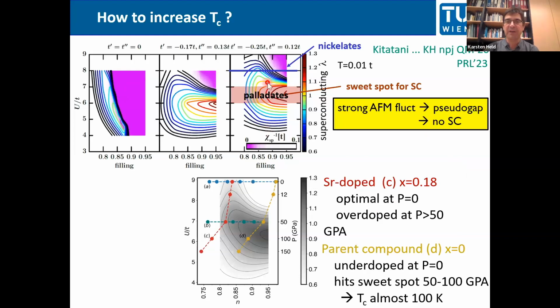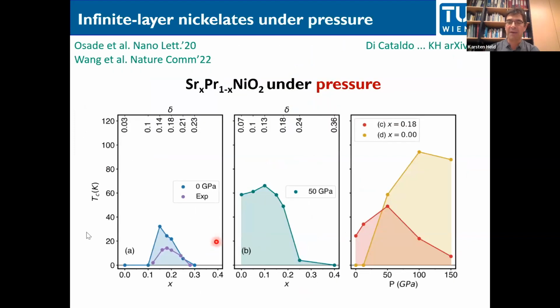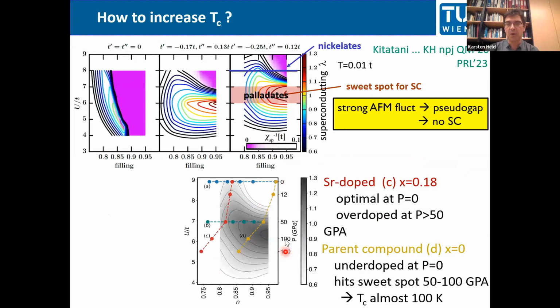Here is again this fingerprint I just showed you. It's replotted here, but now in a gray color bar. So dark regions are good for superconductivity. And we had these 4 paths here: 1, 2, 3, 4 paths. And 2 are at a constant pressure of 0 and 50 gigapascal. That corresponds to a certain hopping parameter and a certain U over t. So it's just going along here. And the other 2 figures were at constant chemical doping and changing pressure. But what is shown here is not the chemical doping, but the actual doping, which includes the electron pockets. And since the electron pockets grow, it's not a vertical line here, but you go in this curved way through your phase diagram.